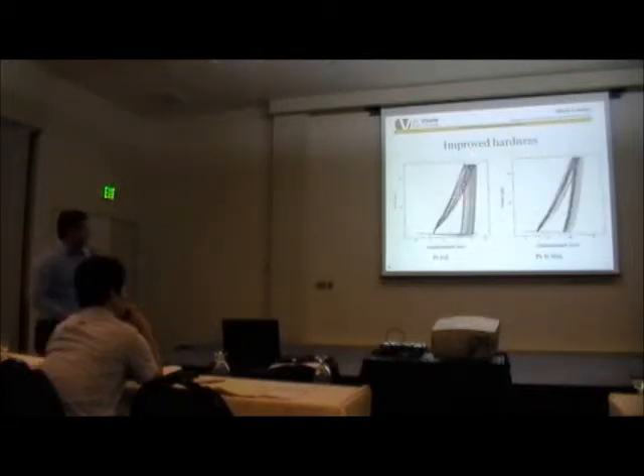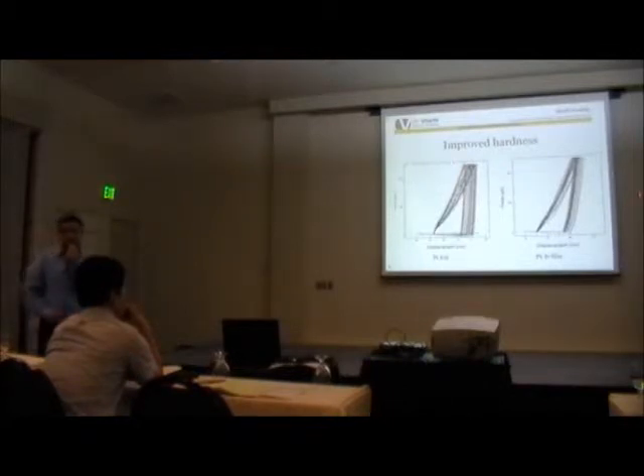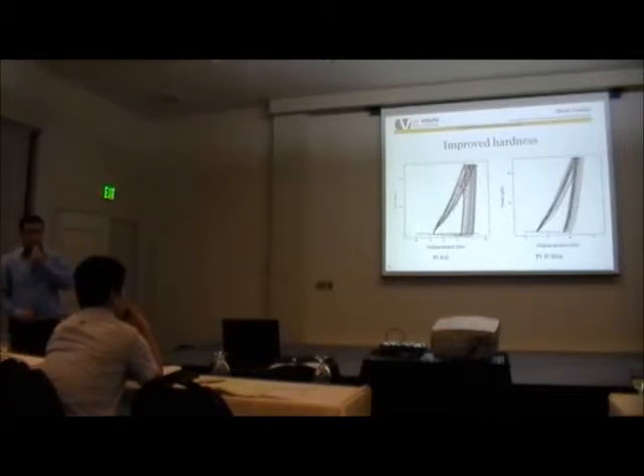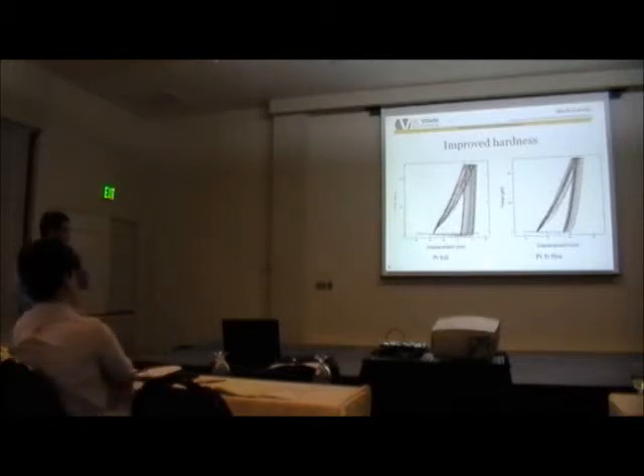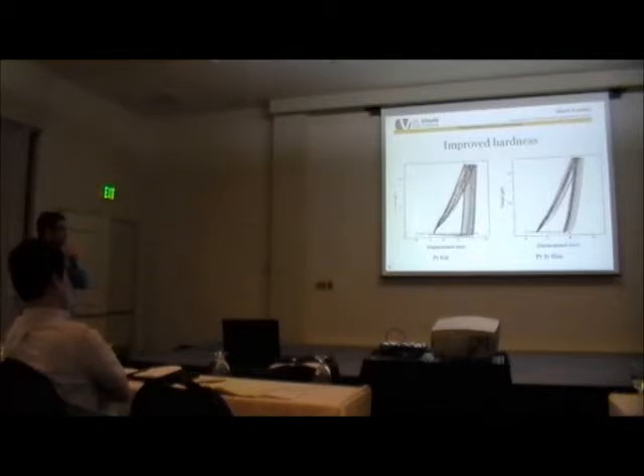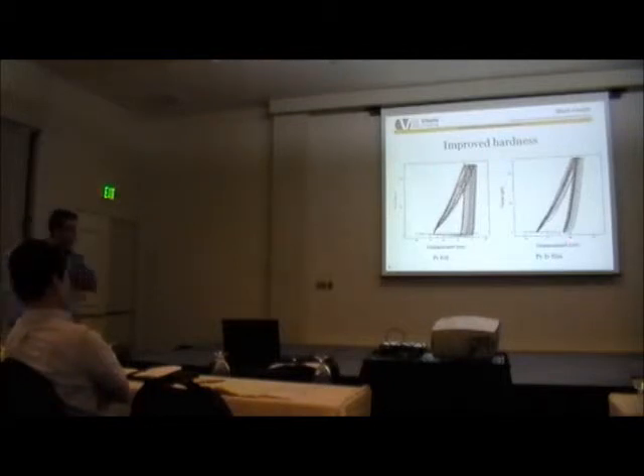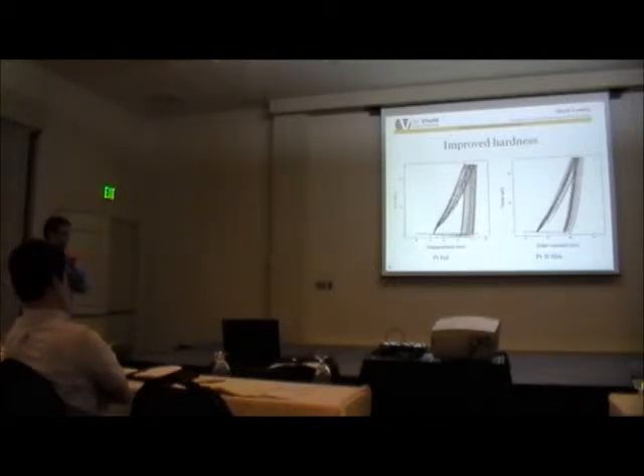Nano-indentation measurements were done in order to measure the hardness of the film, because one of the goals was to improve the mechanical properties. This is an indentation measurement of the platinum foil, which I had just to compare with my platinum iridium film. As you can see on the right side, the indentation depth is almost half of the indentation depth for the platinum foil, indicating that the hardness was increased by nearly 100%.